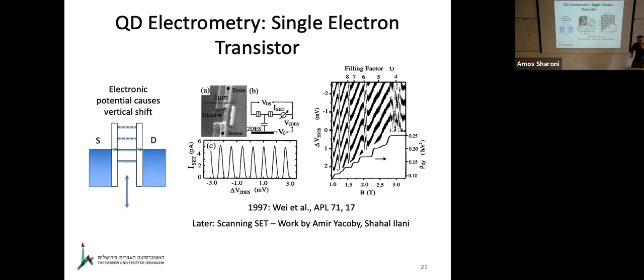A dot can also be used as an electrometer, meaning that it's very sensitive to electric fields. So if I scan the gate here, I get these on and off current signatures going through the dot. That's work done by von Klitzing's group at the Max Planck Institute. And you can see that this Coulomb ladder goes up and down, depending on the electrical environment. That was the first measurement of how the electric field around the quantum Hall system evolves, using a very sensitive quantum dot called a single electron transistor, patterned above the 2D system.